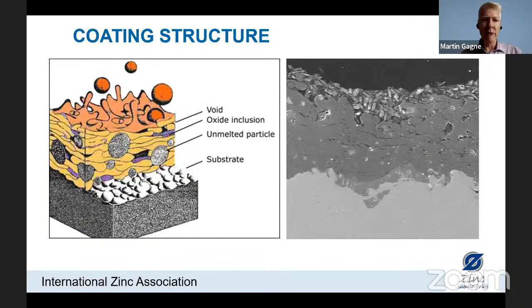So the schematic on the left here exaggerates a little bit some of the features of the coating structure. We can see there can be some unmelted particles. We can have some oxide inclusions as the zinc is atomized and projected through the air. We can have oxidation occur. We can also have voids present where the zinc particles overlap and solidify without fully filling. And then on the right-hand side, this is a cross-section through a coating, and we can see some of those features, some oxides and voids.